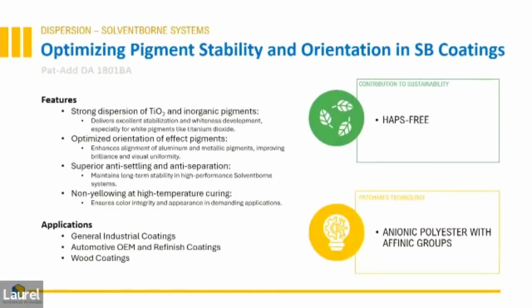And then here's a surface additive that can support your effect pigment orientation in a coating. All right. Typically, we use shear to orient the flake, and then we use gravitational forces and compression forces. As the solvent evaporates, the volume reduces, and that film goes lower in film surface thickness to prevent these particulates from rotating. Now, think about when you have less solvent.